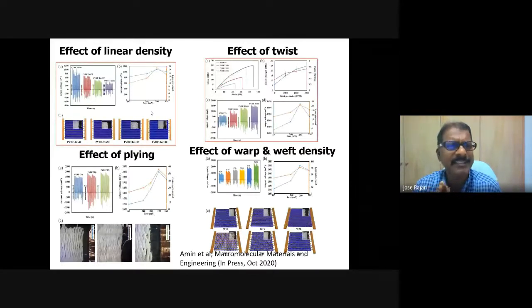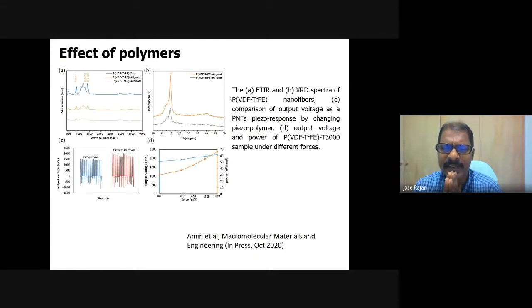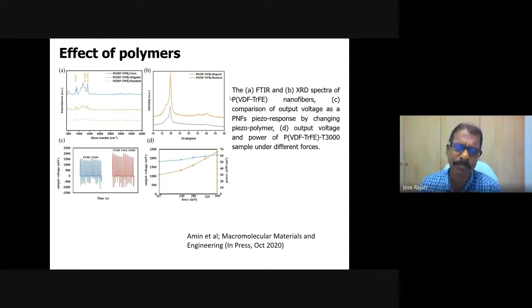And some results I want to convey, and probably a lot of things to investigate, probably using Raman spectroscopy too, is the final piezoelectric voltage that you can obtain. Here, when you look at this slide, this is the effect of polymer. From the geometrical parameters, we isolated the best piezoelectric condition, and then developed a fiber of this PVDF with its copolymer. You would see that we can have a piezoelectric voltage of over 2000 millivolt, meaning more than 2 volts, from a single fiber of about 300 micron diameter and 5.5 centimeter length. We can have that kind of voltage from this piezoelectric yarn.